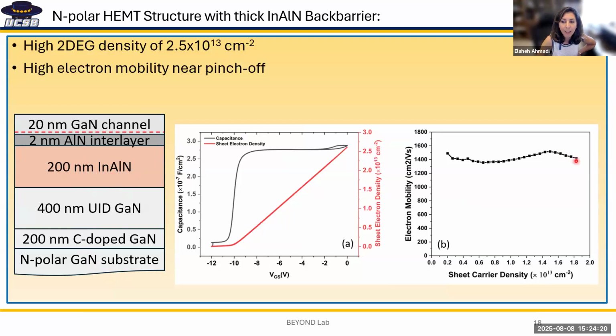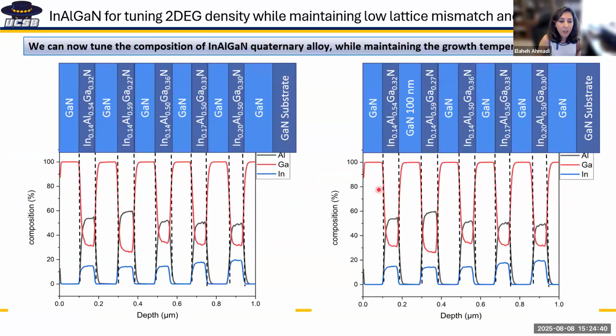And we saw the same thing, that actually the mobility didn't drop. It remains more or less the same, and we can get very high mobilities even near pinch off. And a very high charge at zero bias, near 2E13. Now with